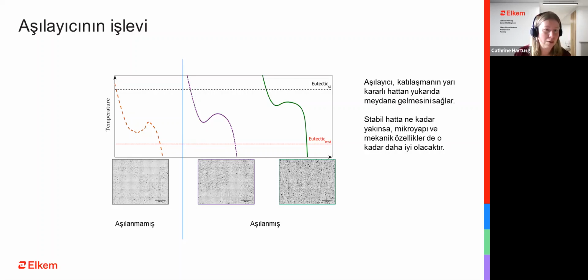And you see the actual curve with the actual structure. As you are improving the inoculation, going from the uninoculated to adding inoculant, but this can be not adding enough, or a different type of inoculant will change how this curve places itself between the 2 lines. But the purpose of the inoculant is that it should lift the line as close as possible to the eutectic, and all the solidification should stay and end before you dip below the eutectic metastable line. But as you can see, with inoculation, the structure improves.